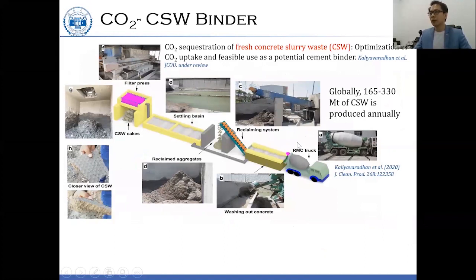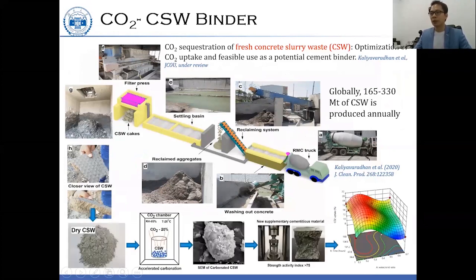This waste is generated from the ready-mix concrete plant during the reclaiming process to recover some of the coarse aggregates. After the process, we are able to collect the CSW and dry it in our lab, and we found that it contains a certain amount of fine aggregate and unhydrated and hydrated cement particles.